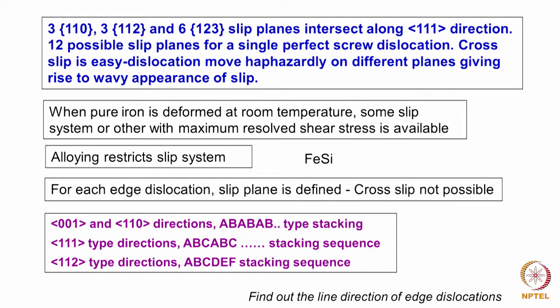directions, for each of the directions we can look at how the atomic layers are packed. If you look along the 001 direction, it is an AB type of stacking, whereas if you look along a 112 type of direction, it is a 6-layer stacking sequence, ABCDEF, ABCDEF, like that it goes. Along the 111 plane, the packing is ABC. Along the 110 plane, which is the close packed plane, the packing is an AB type of packing.